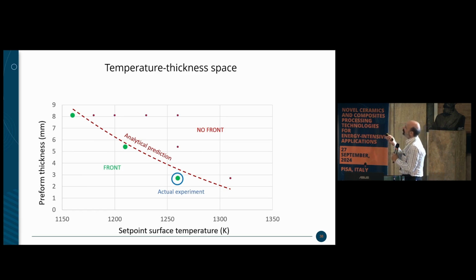Well, we can collect all that in a temperature thickness space here, for example, in which you have a dividing line between the existence of a front or the non-existence of a front, or the correct situation and the undesired situation. And, well, here what we see is that the actual experiment is on the good side, and if you increase the thickness, you can rapidly enter the domain of inefficient infiltration, okay?